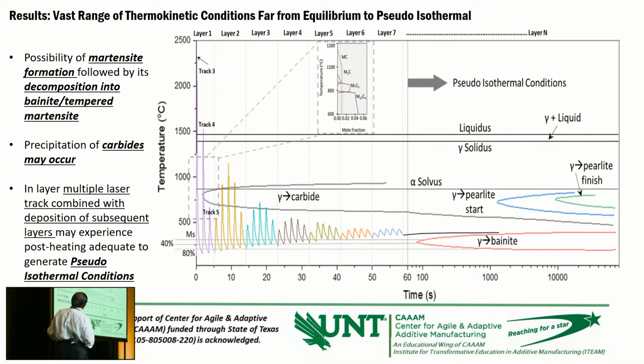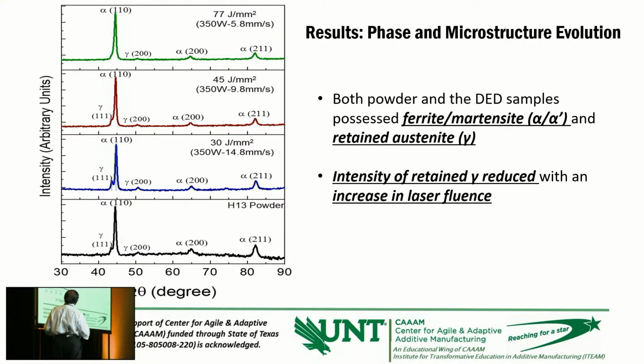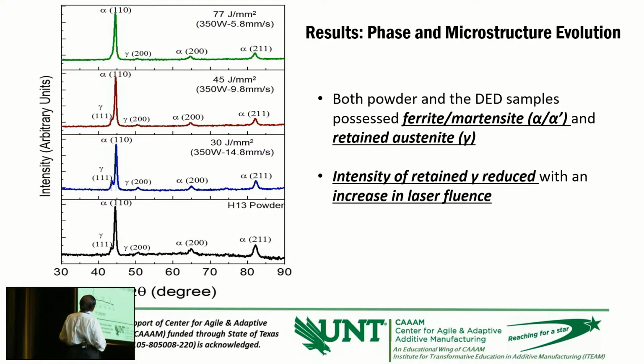This is layer 1, layer 2, layer 3, layer 4, layer 5, 6, and the kind of temperature it reaches maximum, and so on. And also, it shows what can happen during these thermal cycles, given by this Thermo-Calc-based prediction of the phase transformations. Again, what we did experimentally, we studied what phases exist in this AM process sample by X-ray diffraction, and these confirm that these phases do exist at these temperature transformation regimes and so on.